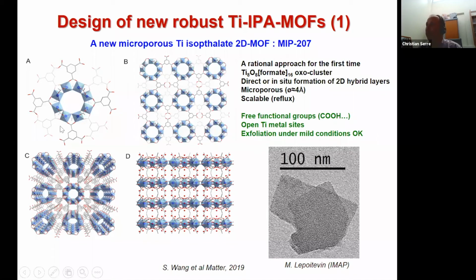Here we could obtain the titanium formate oxocluster, which is the Ti8O8 oxocluster. And then, either by direct synthesis or by simple exchange with isophthalic acid, we could keep the building unit during the synthesis and produce this 2D material where the clusters are bridged in the plane by the ligands. At the top and the bottom of the building unit, you have acetate or formate that finish the coordination. So this phase is microporous and has open metal sites, and it can be exfoliated.